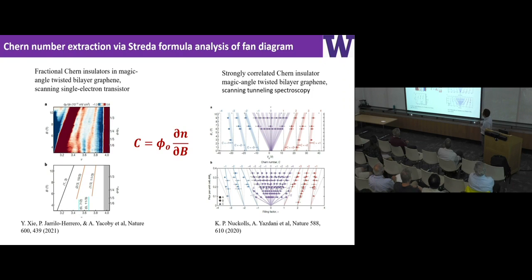There are two ways to measure the Chern number. One is to just do transport, if you can. If you cannot, then you measure the Wannier diagram and use the Streda formula to fit this dispersion curve. So look for this thermodynamic evidence of the states.